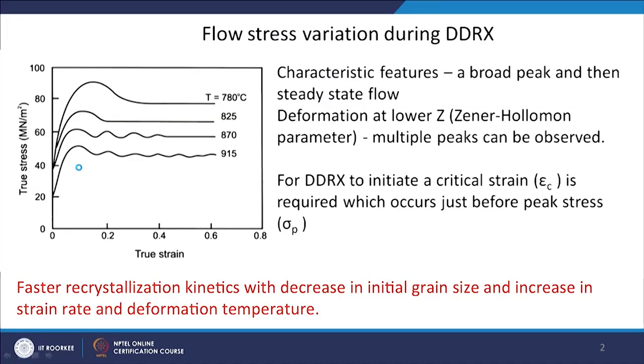We have already seen this stress-strain curve or flow stress curves, and you can see when you have discontinuous dynamic recrystallization the flow stress curve has this kind of a peak, and then it comes down and more or less it becomes a steady state. As a function of temperature, if you see, the temperature is increasing, so flow stress is reducing.